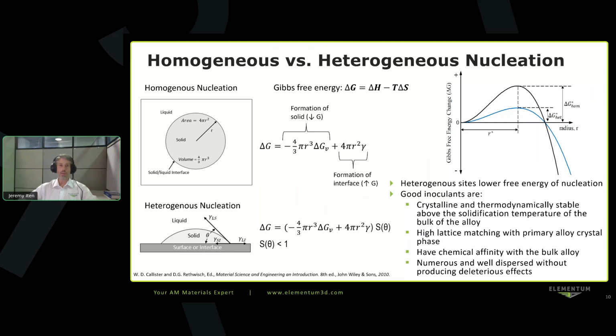The math behind this is essentially that you're reducing the barrier of nucleation. When you are forming a nucleation crystal, you have surface area interaction energy that is kind of unfavorable. You don't want a lot of surface area interactions, but your volume energy change when you're below the solidification temperature, below the melting temperature of the material, that's favorable.